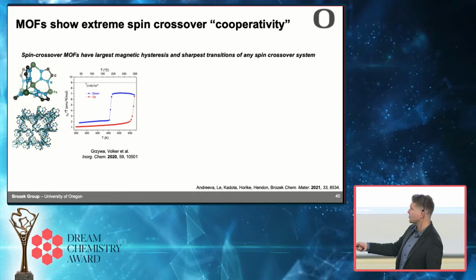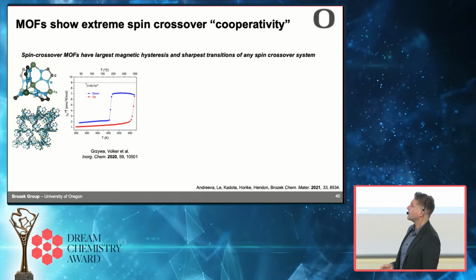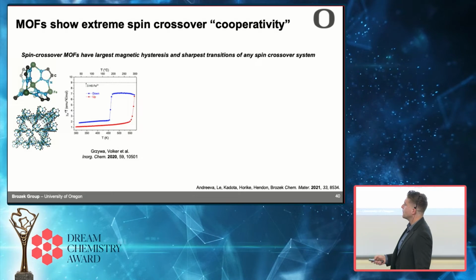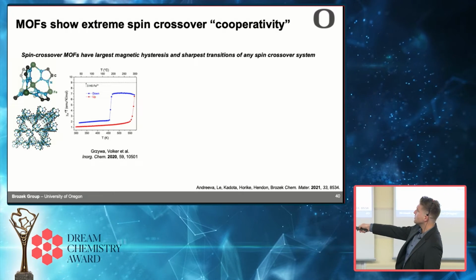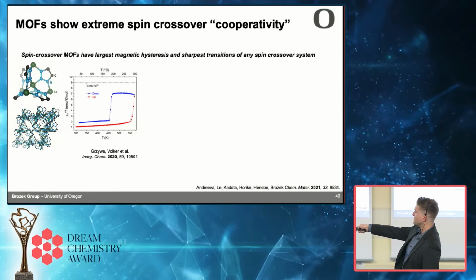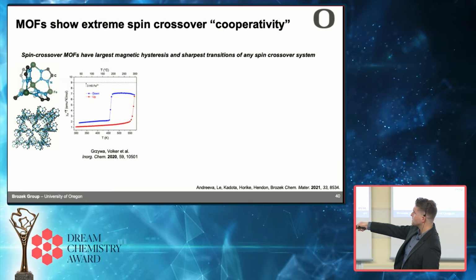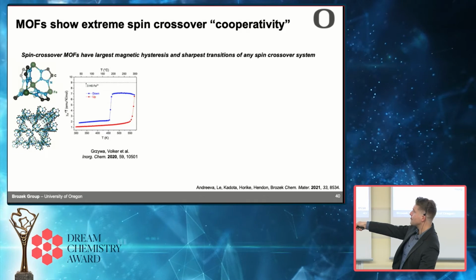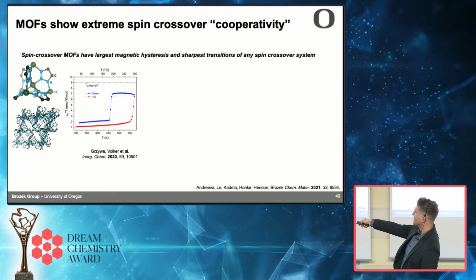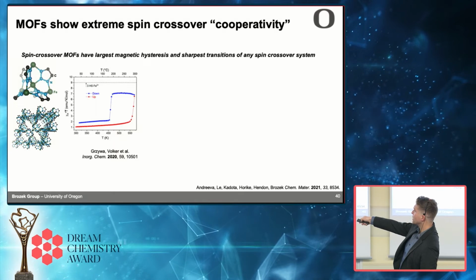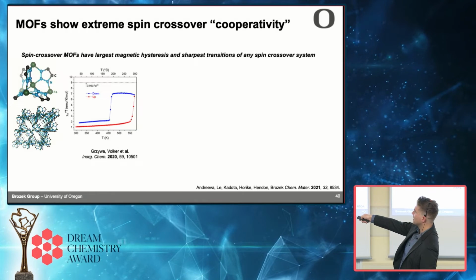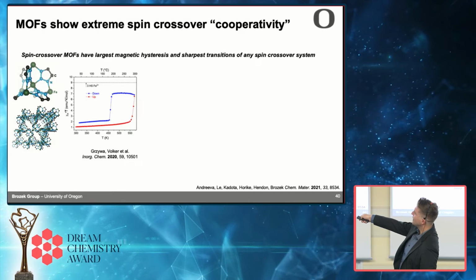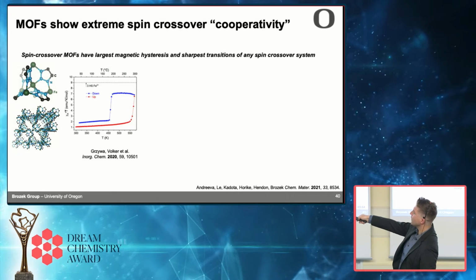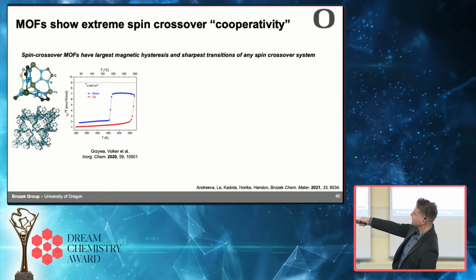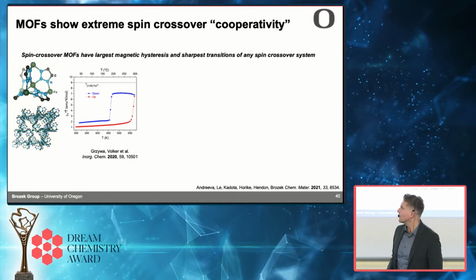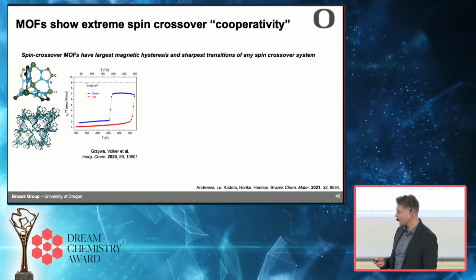So there's a MOF called iron triazolate that is a spin crossover material. And what that means is that if you measure the magnetic moment as a function of temperature, the material would stay in a non-magnetic state, in this case, a low spin state. And then at some temperature, it flips into a high spin state. You cool it, and it'll stay in that state for a very wide temperature window until it suddenly flips back down into the low spin state. So that's peculiar behavior because